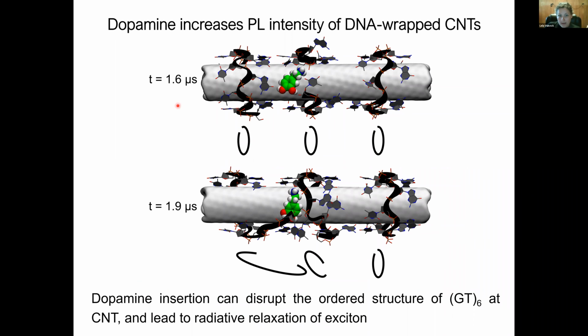And then we also wanted to check, what does dopamine do when it binds to the nanotube? Here is dopamine binding to these ring-wrapped nanotubes. And we simulated for a pretty long time, about 2.5 microseconds. So dopamine didn't do much. It bound to the nanotube surface over the first 1.5 microseconds, but eventually the binding of dopamine led to the distortion of the rings, so distortion of these periodic potentials. So we think that dopamine insertion can disrupt the ordered structures at the nanotube surface, and then that could lead to radiative relaxation, meaning light emission of the nanotube.